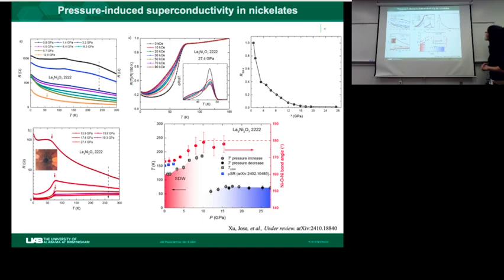So first of all, this sharp drop, we didn't see the zero resistance. Zero resistance is a confirmation, right? Whether you have true superconductivity. However, in this case, there is some argument that this phase could start with a 1313 instead of a pure bilayer. People have done TEM to show that. And in our case, we intentionally started with a 2222 phase, which is supposed to be the superconducting phase. And still we see the resistance didn't go to zero.